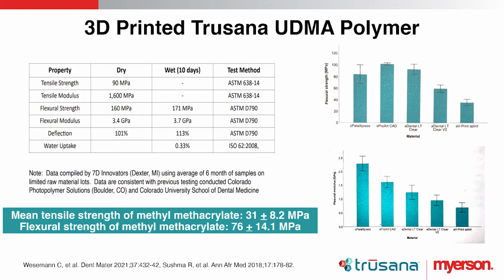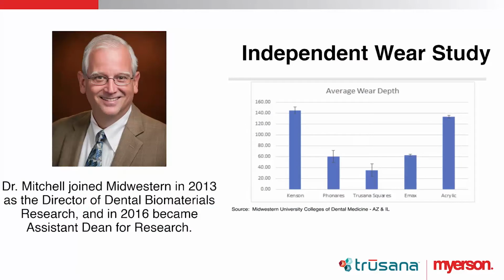Now, we have a pretty good idea, a prediction on this. Why? Because we've submitted this independently to Midwestern University, and John Mitchell has done a wear study using zirconia antagonists and found out, and this blew my mind, that it beat Kenson. Well, that didn't blow my mind, but it beat Kenson and it beat Phonares, but it also beat lithium disilicate. It was more wear resistant than lithium disilicate. So that was impressive, especially since it didn't come out of any of Dr. Swartout's work.